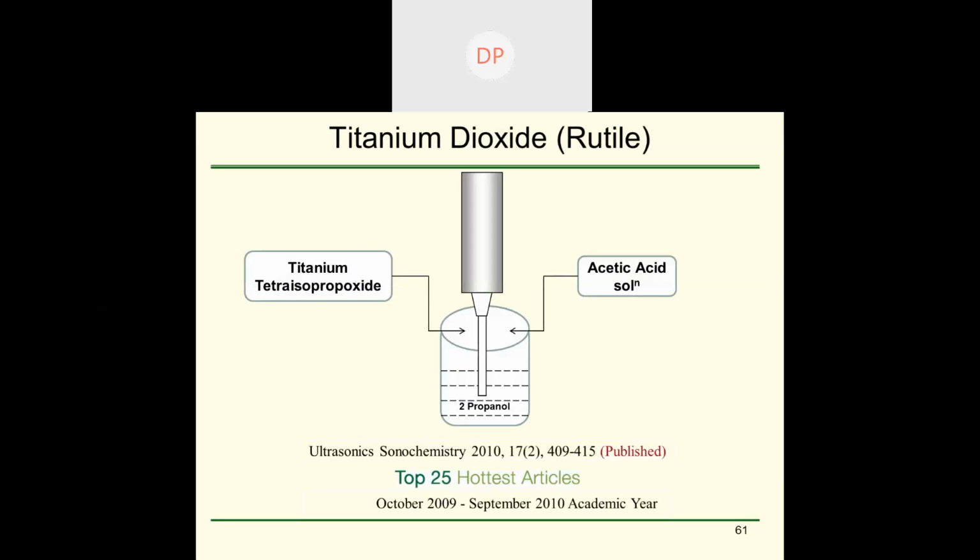In this reaction, we have taken titanium tetraisopropoxide, acetic acid and 2-propanol, and we have prepared the sol, and we have given an additional 10 minutes of ultrasound, and at the gel condition, again we have given ultrasound for 10 minutes.